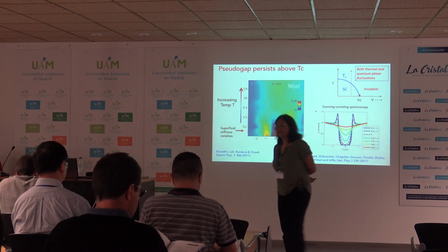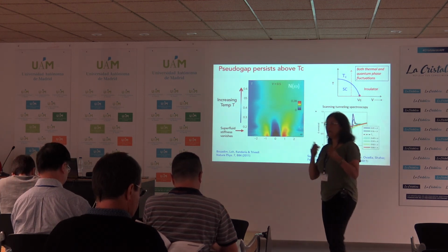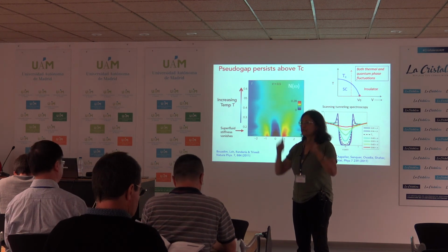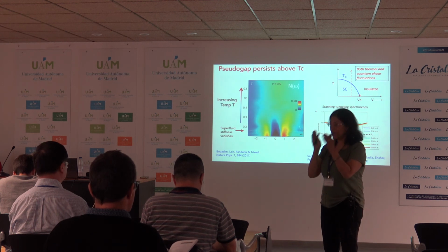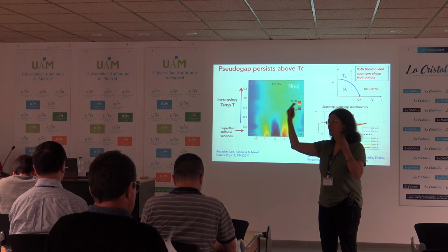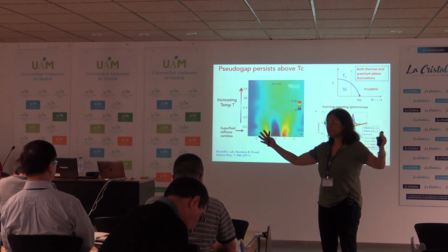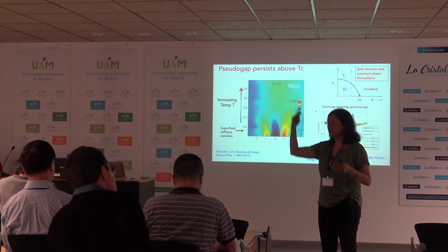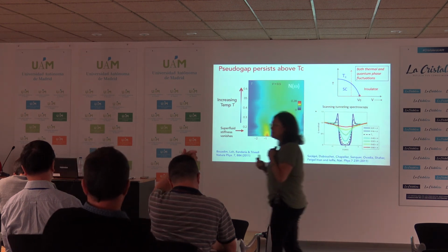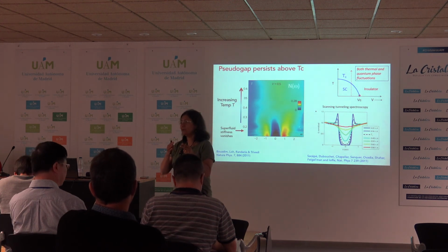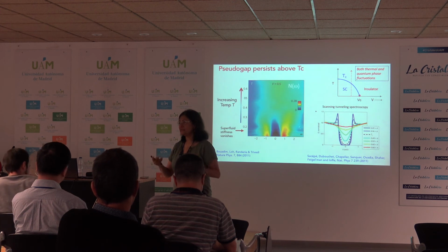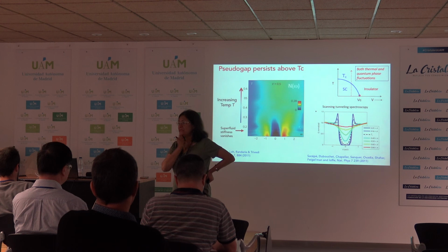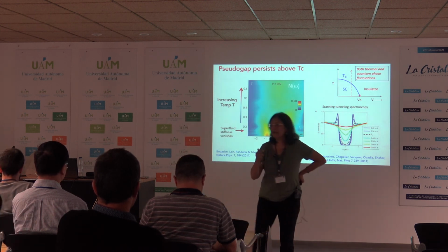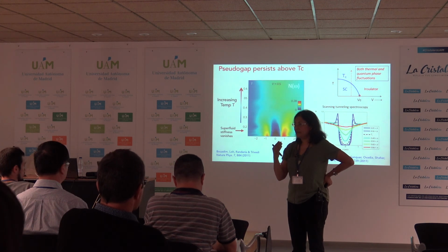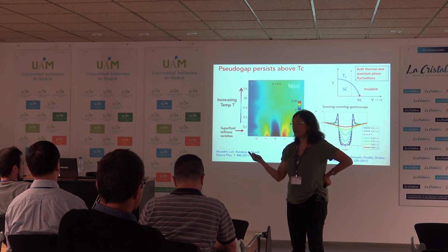Right. So you could take an experimentalist point of view that you will look at the minimum gap, and so you're basically looking at the two measured quantities, the gap and the stiffness. The stiffness is an overall macroscopic quantity, but the gap depends on each band. So you could compare your rho s with the minimum gap and see where that switches to give you an idea about the BCS-BEC crossover. You could also extend the whole thing, especially if there is information on each band. You could look at the band bending on each band. And then some bands could be in the BCS regime and some could be in the BEC regime.